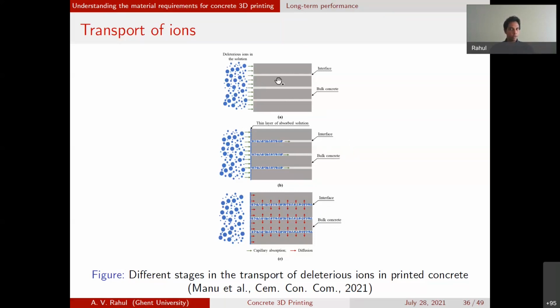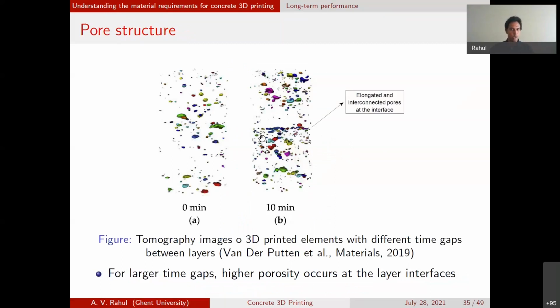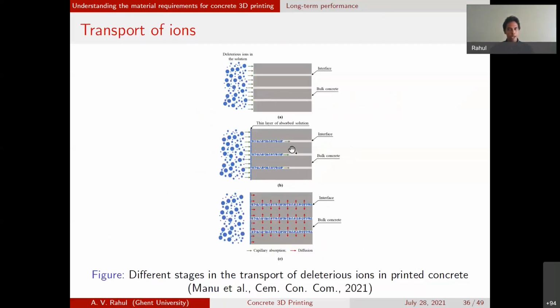If you have elements with larger time gaps, as you show here, what could possibly happen is that larger ionic movement can occur through the interlayer, as you see in these images here. This usually happens through capillary absorption. But in the region of the bulk concrete where there's no interlayer, you see, this is an exaggerated image, there's much lower ingress of ions through capillary absorption. On the other hand, a large amount of capillary absorption can occur through the interlayer. But once the interlayer has become sufficiently saturated, further progress can occur inwards by diffusion.